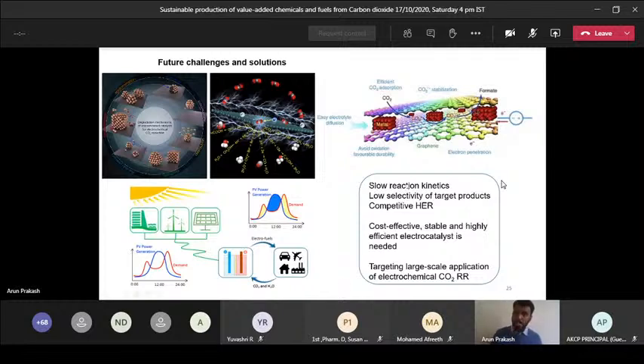The other challenges you have to think about are low reaction kinetics, low selectivity, because multiple products are formed, and competitive hydrogen evolution reaction. You have to minimize the proton adsorption energy, then you can overcome the hydrogen evolution reaction. And cost effectiveness, how low cost a catalyst you are going to prepare, that matters, because these are all industrial processes. You cannot prepare a catalyst with like $1,000 or more than that. You can't put a lot of money into producing a single chemical. So you have to consider the cost and stability.